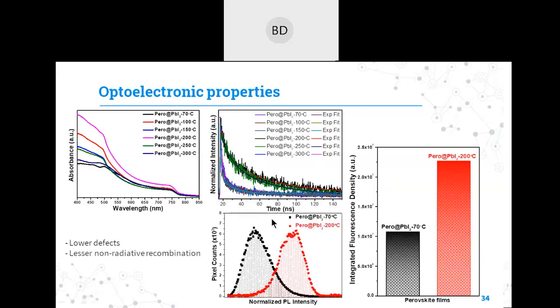We have done some capturing of fluorescence using confocal microscopy, and we came to know that the fluorescence density throughout the film has been increased significantly. If you see, as compared to the perovskite film prepared at 70 degree PbI2, the fluorescence density is very low, whereas the fluorescence density for the 200 degree annealed film is around 2.5 times 10 to the power 7, which is more than twice as compared to this film. This shows that a very significant amount of defect states has been reduced in the perovskite structure for this film, and this reduction in the perovskite defects reduces non-radiative recombination and can give an increase in the emission process.